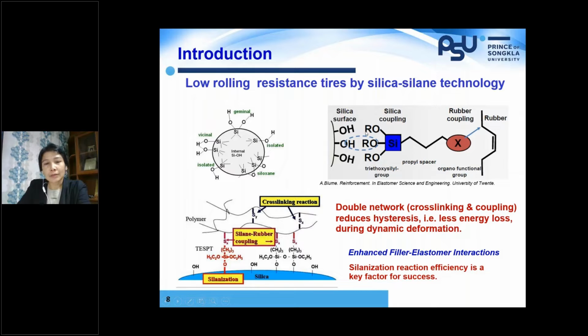For the coupling reaction between the silica and rubber, as you can see here, we have silane in the middle. By having the silanization reaction driven during the mixing process, we will have the silane molecule attached, or covalently bonded, to the silica surface, leaving the polysulfide functional group to attach to polymer molecules during vulcanization.